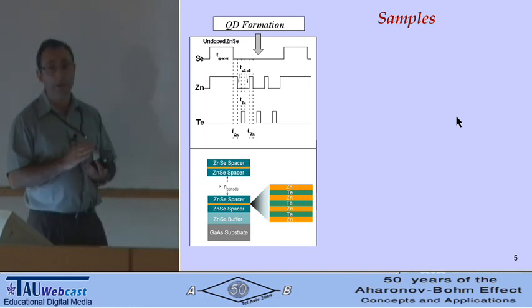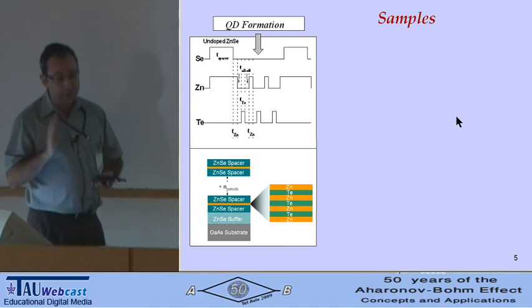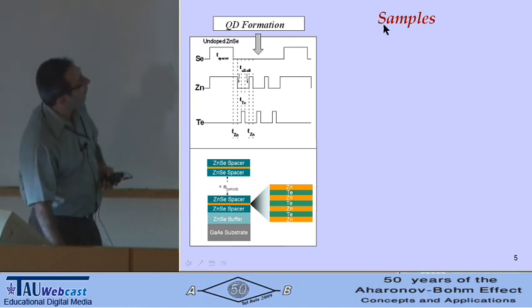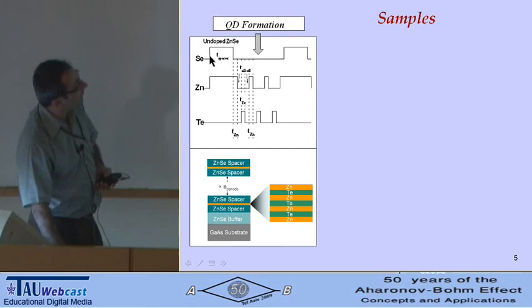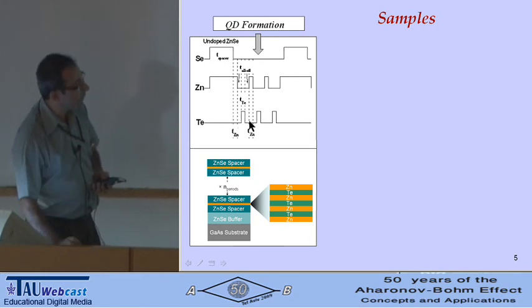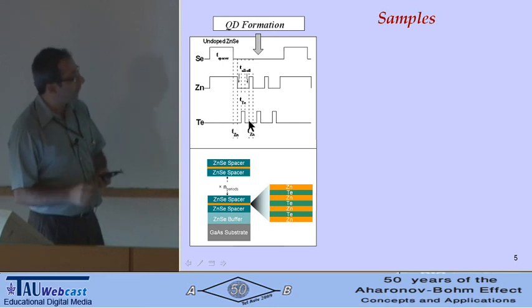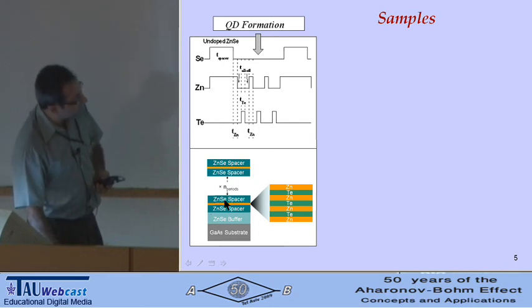Ours are not grown the same way. They're grown in a little bit more complicated way. So we first grow the barriers, and then we use so-called migration-enhanced epitaxy, where each element, zinc and tellurium, is deposited sequentially, with time for tellurium to find its minimum energy position. And kind of schematically, we show it here.